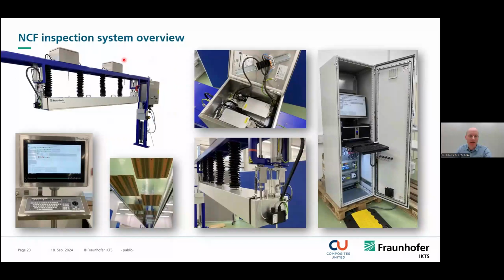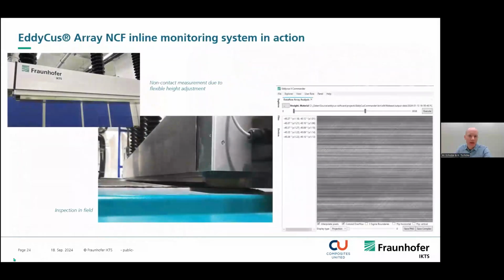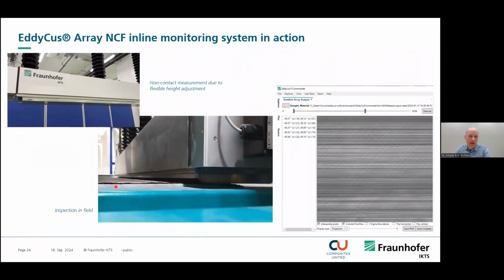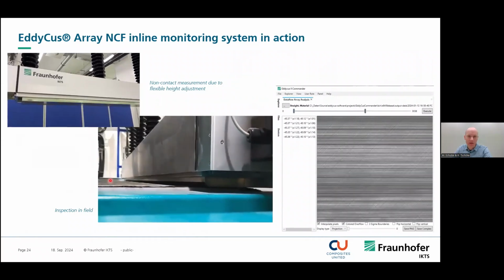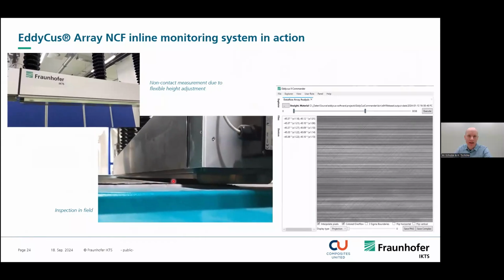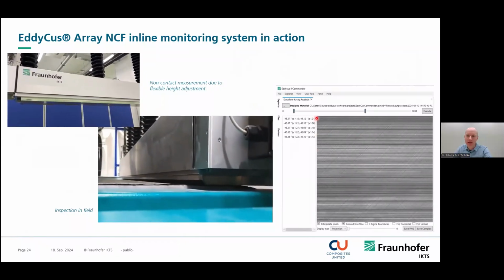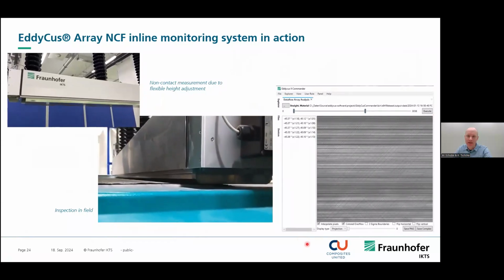So that's the device. We have 4 eddy current channels in this cabinet here. Here's the eddy current array. We have a mechanics to lift up the whole array. That's an ATEX certified HMI, and the PC where all the calculations and the parameterizations are done. Here we see the system in the field. So we have a little lift-off, so we don't touch the surface, and in parallel at up to 5 meters per minute we can generate these eddy current C-scans. That's quite impressive.